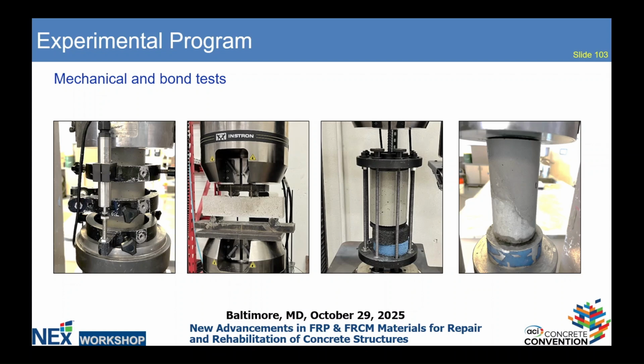And on the fourth, here we can see a cylinder. Half of the cylinder is made up of conventional concrete, and half of that cylinder is made up of polymer concrete. The conventional concrete wedge was first prepared, and then we used sandpaper to remove the debris or dust from the surface, and poured polymer concrete into it to test the bond between conventional concrete and polymer concrete.